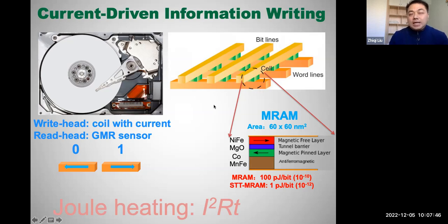Similarly, for our MRAM devices, that could actually replace the DRAM in our current computing technology. For this MRAM device, the key elements are still ferromagnetic materials, for example, nickel, iron, cobalt. They are only a few nanometers thick, maybe even less than 10 nanometers thick. The feature size of this kind of MRAM device is around 60 nanometers. But for writing the information in this kind of device, you still need to inject the current, either using the spin transfer torque or using the spin orbit torque. Anyway, you have to use the current to generate a stimulus for the magnetization in current magnetic memory devices. That means the Joule heating is inevitable.